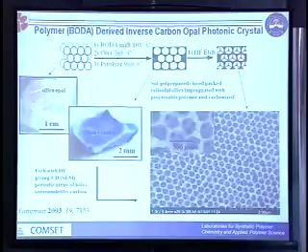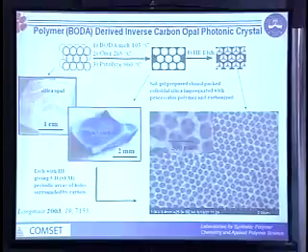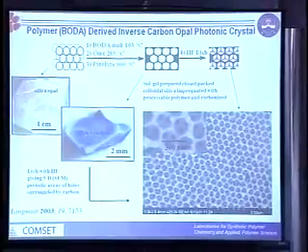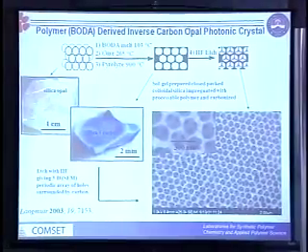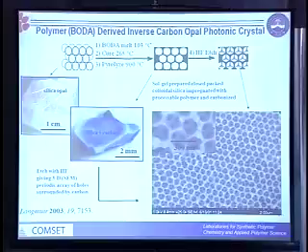But as far as nanomolding goes, we can take these very, very processable resins and take something like a silica opal, which you can make. You can buy the silica spheres and close pack them and let them arrange in a hexagonal array, or you can make them. And so we've done that. Here you've got an opalescence from these little close-packed, monodisperse silica spheres. And then you can take your monomer and impregnate all this void volume. Of course, the color changes because you've changed the dielectric contrast, and it's a photonic crystal. And so the color changes, and this has been pyrolyzed, and then you can simply etch out the silica and